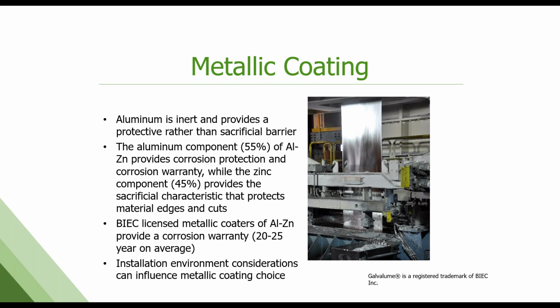So why do we do this? Well, it's all about corrosion, right? We all know that steel doesn't hold up real well out in the real world unless it's got something over it. On the Zincalume or Galvalume product, you've got two things going on. The aluminum portion provides an inert protective barrier, whereas the zinc is a sacrificial barrier. So the zinc will corrode away preferentially over time to protect the steel, whereas the aluminum stays in place and is fairly inert long term as well. Like I said, the BIEC licenses coaters to make this product. Most producers are offering anywhere from a 20 to a 25-year warranty for corrosion perforation on this product. There are some exceptions, of course, near the ocean and in industrial environments. So you do need to read those warranties carefully and make sure you're getting the right product. Next slide.